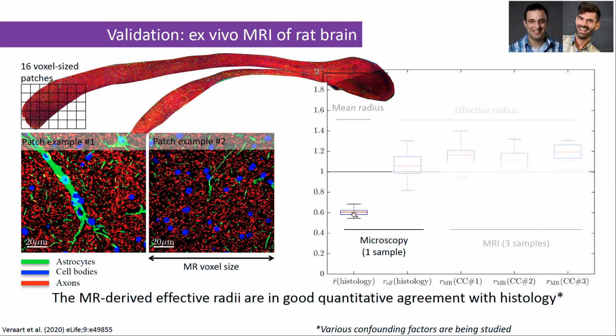Now, we know that with MR, we're not measuring the average radius. So in order to facilitate a more honest comparison between MR and histology, the first step was to compute the effective radius that corresponds to our histological data. So we computed the sixth-order moment of every distribution, the second-order moment of the distribution, we computed the ratio, and we reported this value. And we can see that our apparent radius increases quite a bit. By stepping from the average to the effective radius, we almost double our nominal value.